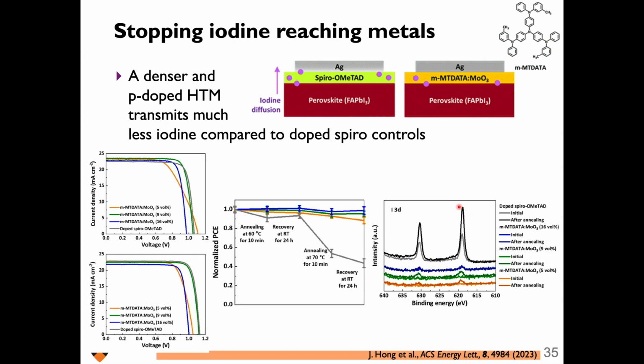If you look at the Spiro system up here, you can see that the reason it's on the top of this waterfall plot is there's so much iodine in that system. And you can see after annealing a lot more of it. But if I take something that holds back iodine, in this case this composite of m-MTDATA and moly oxide, you can see that it manages to keep in check the iodine in that hole transport layer. And as such, it can really withstand substantially more stress at higher temperatures. So 60 C isn't enough to do much, but 70 C is already enough to absolutely destroy the conventional doped Spiro system. And I think that has a lot to do with iodine oxidation and infiltration into these media.